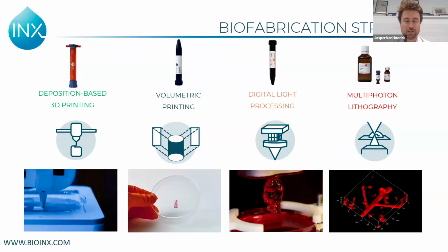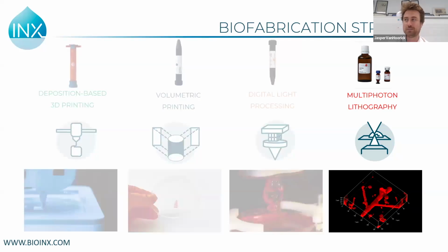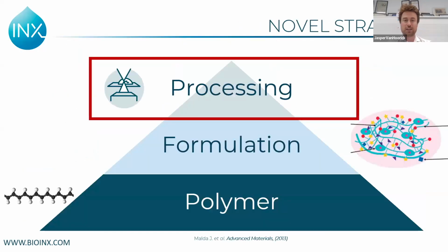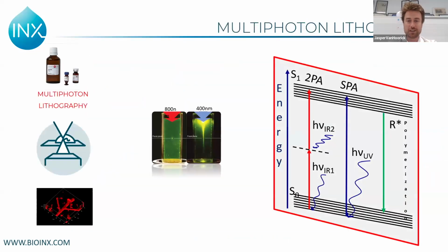So if we look at the different printing technologies again, let's go into the other extreme. So we started at the low resolution. Let's go immediately to the highest resolution technology, which is two-photon polymerization or multi-photon lithography. So here, how does this technology work? Basically, instead of single photon, you use 2-photon. I will not make it too complicated, but what happens in any photo-induced reaction is you excite your electrons to an excited state, and when they fall back, they release their energy and they do something. In this case, in printing or in cross-linking, upon releasing their energy, they initiate polymerization.